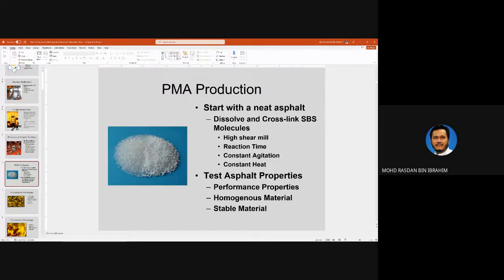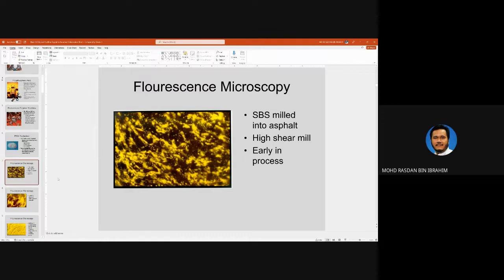You need to mix and immediately use, because if you mix it, it's hot, and then you just leave it there, the polymer will settle to the bottom of the barrel. So when you use the barrel, the bitumen in the barrel, the mix is not homogeneous. You get one patch of very thick with the polymer, and the other part is very low viscosity. So typically using SBS, if it is milled in a high shear mixer, the distribution of the particles is very good.